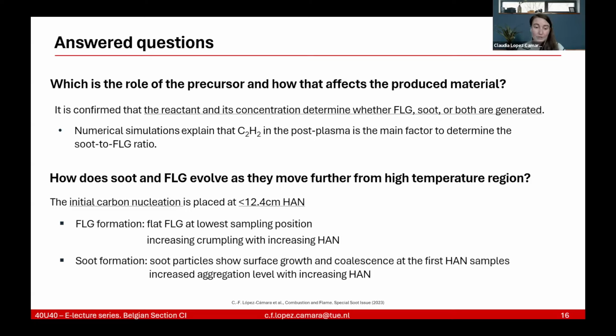For the soot formation, though, the soot particles show surface growth. That's what explains that the median diameter is larger, even though the BET area is lower. And coalescence at the first height above nozzle samples, and an increased aggregation level with increased height above nozzle as well, which I did not show, but we saw that too.